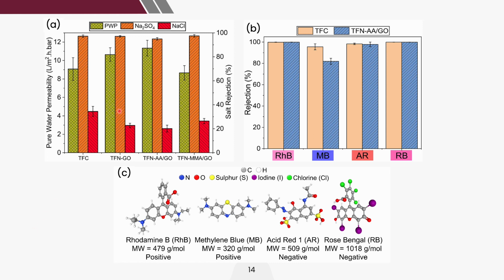This is data of the different membranes for the pure water flux and salt rejections. For the control TFC membrane of the mixed IP technique, the flux is about 9 LMH per bar. And upon incorporation of graphene oxide, you will see that the flux further increases. This is due to the hydrophilicity enhancement on the membrane surface. When you use the hydrophilic monomer to modify the membranes through the GO incorporation, you will see the flux can be